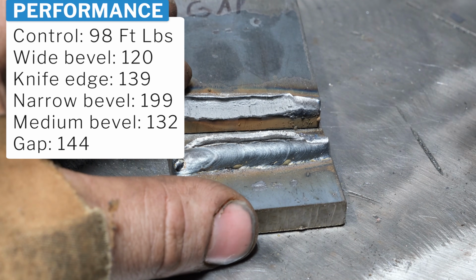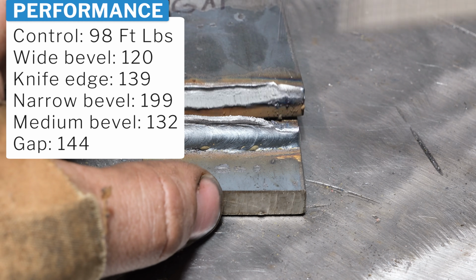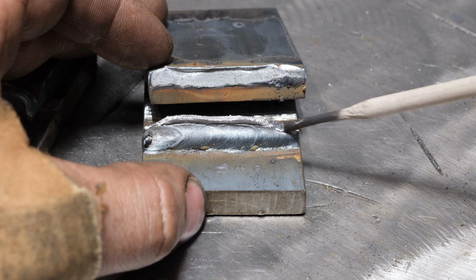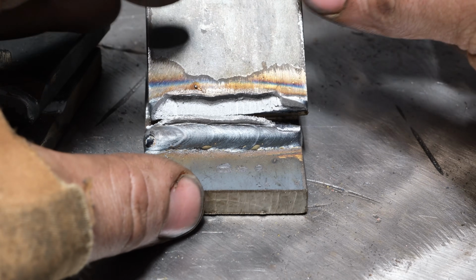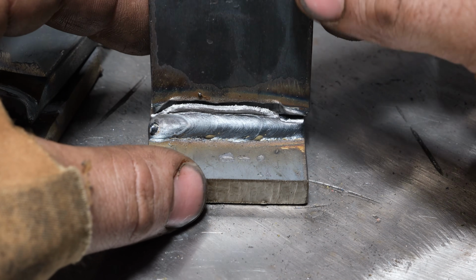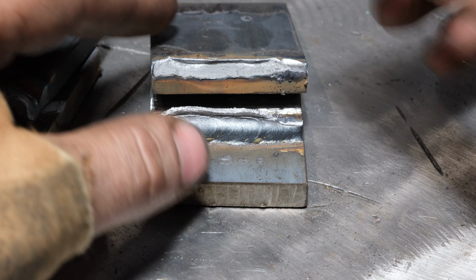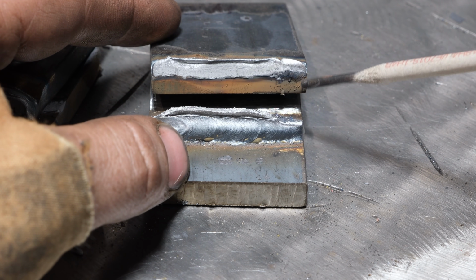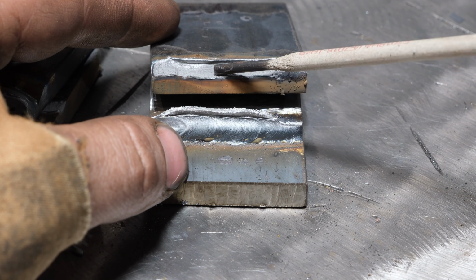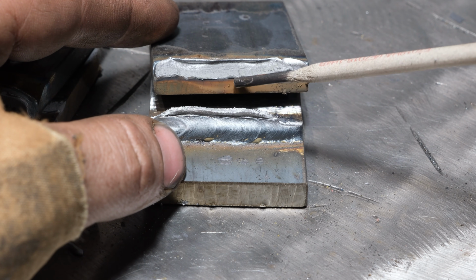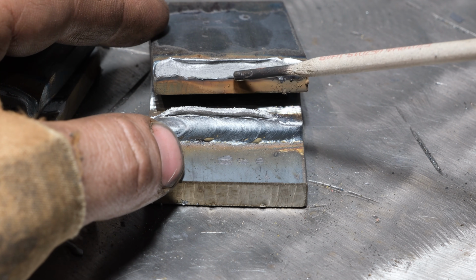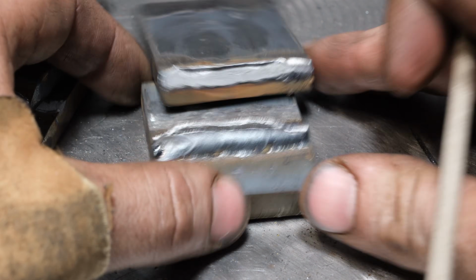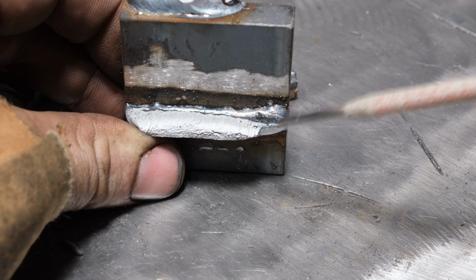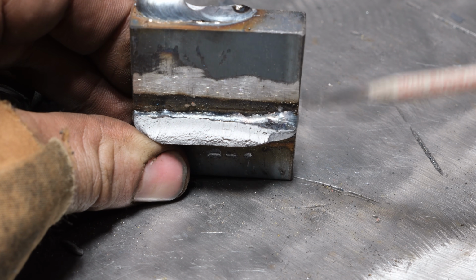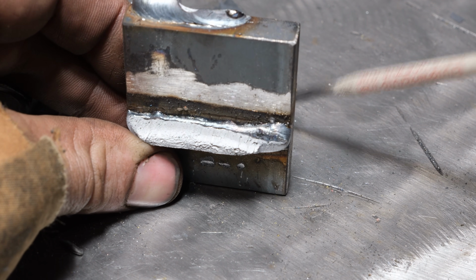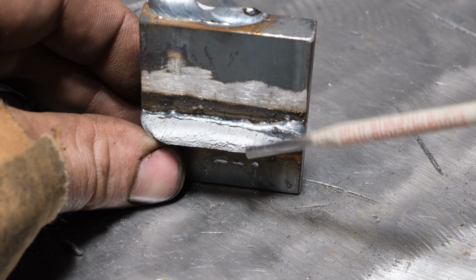Now the gap performed really well, better than some of the other ones, and it clearly stuck to the bottom plate very well. The top plate here, it tore quite a bit out of it, which I would say is a good result overall. And we did not achieve more than halfway fusion in that, because remember, this just had a gap and no bevel. Well, it penetrated somewhere around 1/8 and fused that, and that was it. When you look here, you can see there's clean metal down in here where it wasn't even obviously touching anything because of that gap, and then it broke off here.